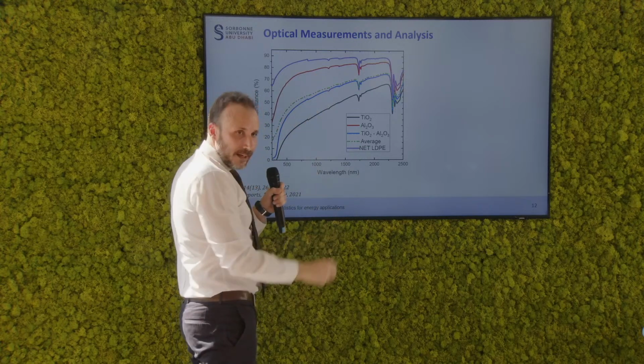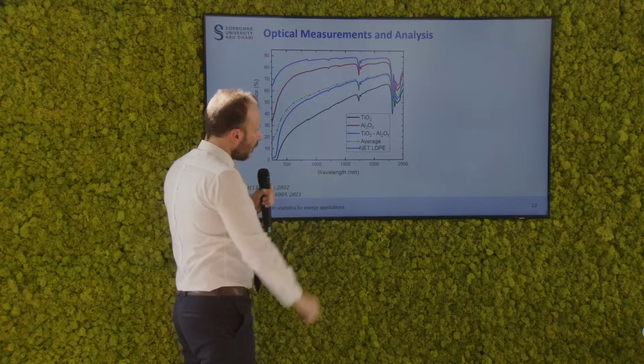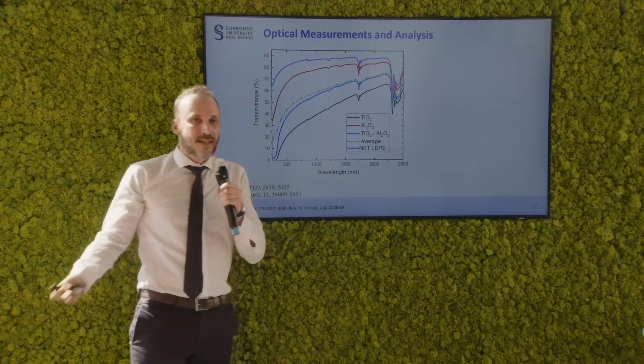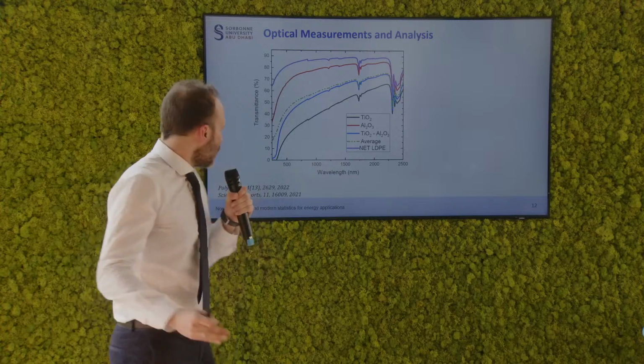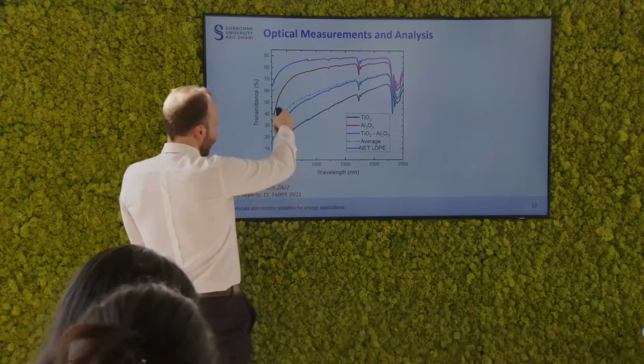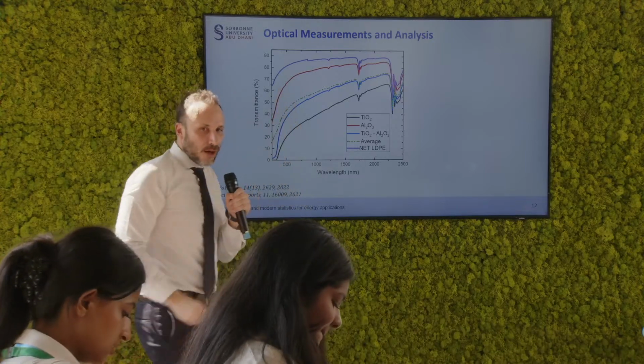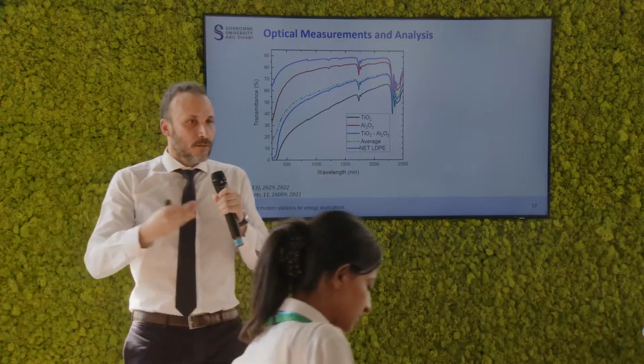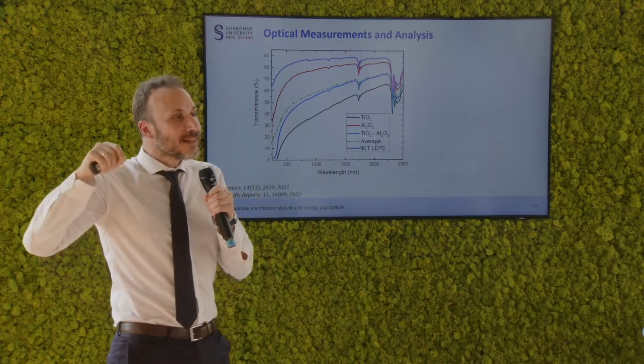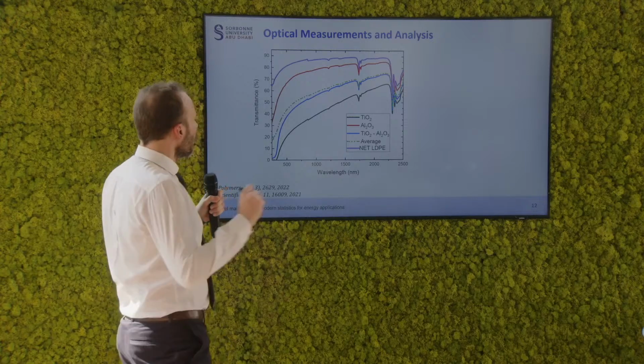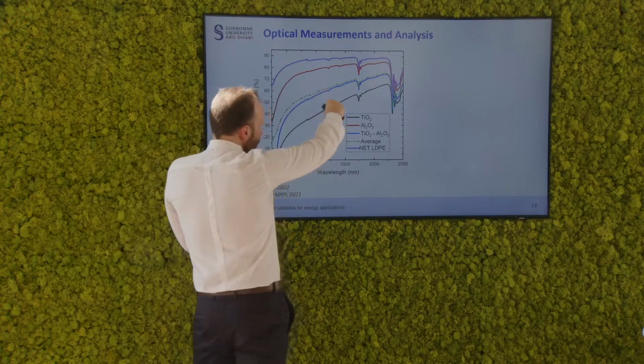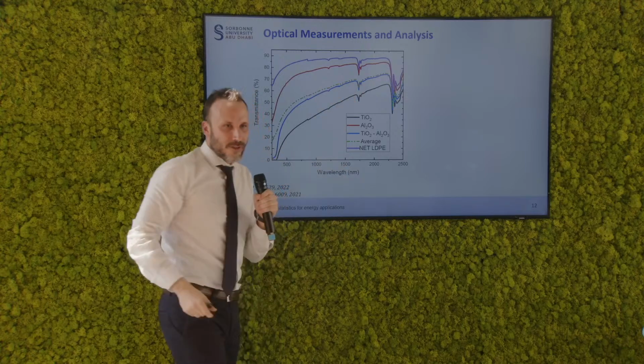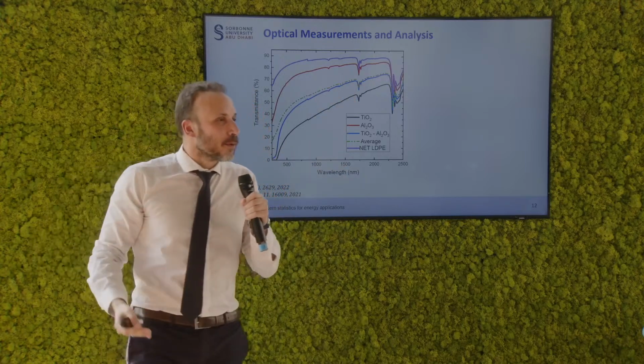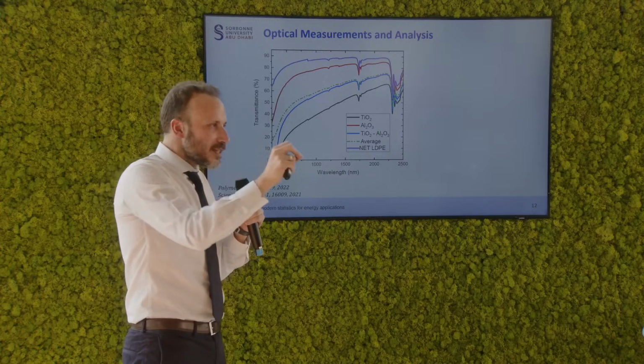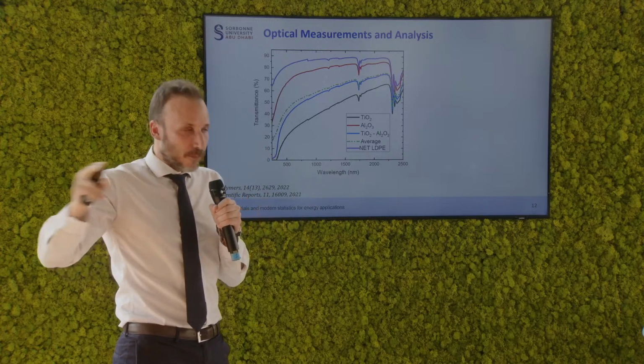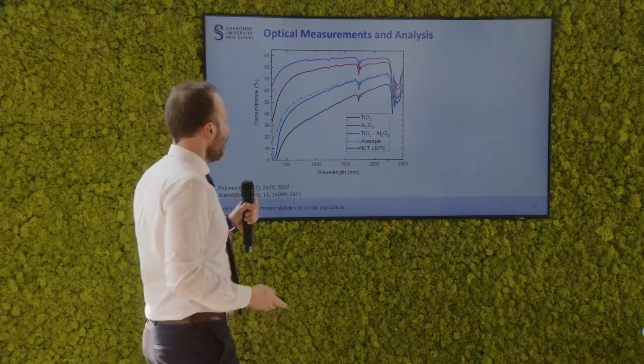Now, as we start adding nanoparticles, this curve shows if we add alumina, this curve shows if we add titania alumina, and the final one over here shows us a sample that only contains titania. You see that, first of all, gradually and effectively, we can completely remove the part of the spectrum which is close to the ultraviolet, while at the same time we are able to regulate the intensity that passes in the visible and in the infrared region. So that is a proof of principle that we can actually regulate which areas of light can pass through, can propagate through the films, and which cannot.